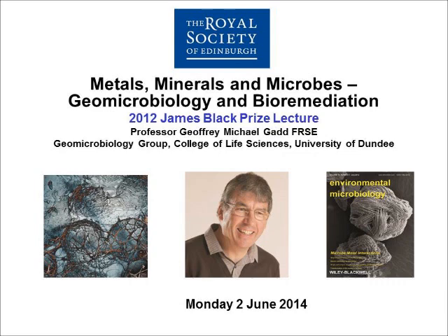And there are some small examples of these mortar cubes, using cobalt as an example. Cobalt's one of the radionuclides, and it's quite useful to use because it's colored, so you can see removal of the color from this leached mortar block, showing removal by the biomatrix that was on top of it, after a couple of weeks. We found it also effective for multiple metal contamination. These are the main radionuclides of interest in that particular study: cobalt, cesium, and strontium. You can see removal quite effectively.